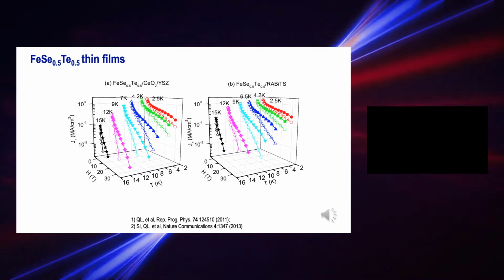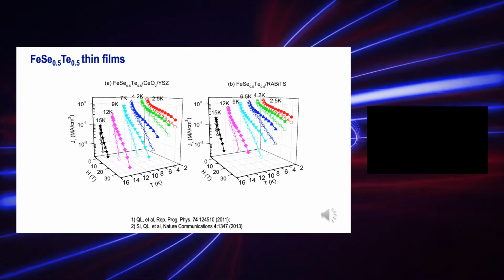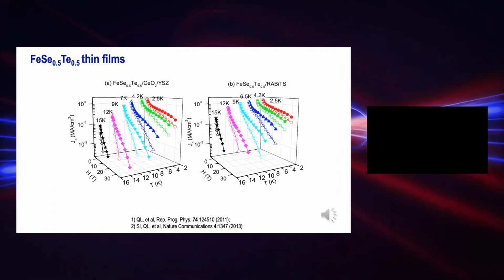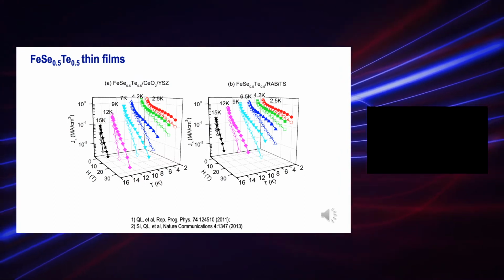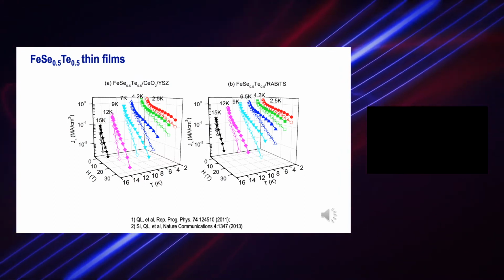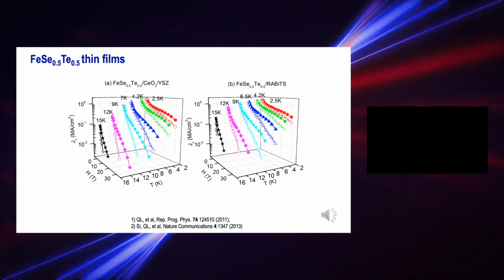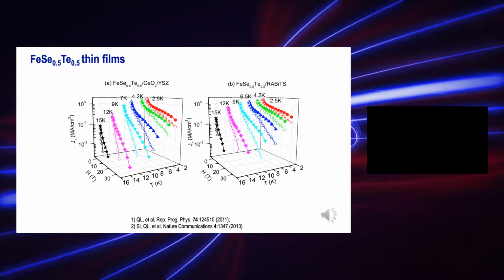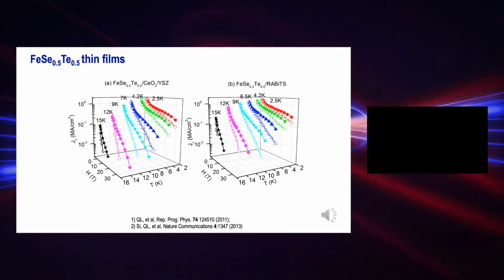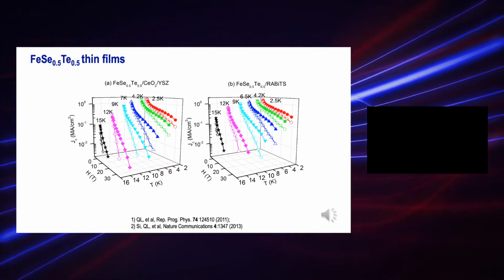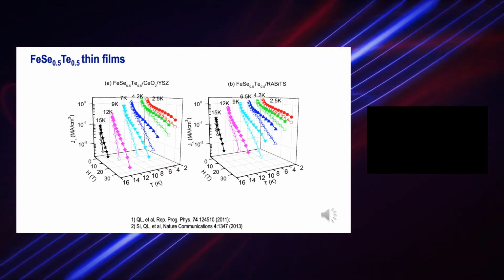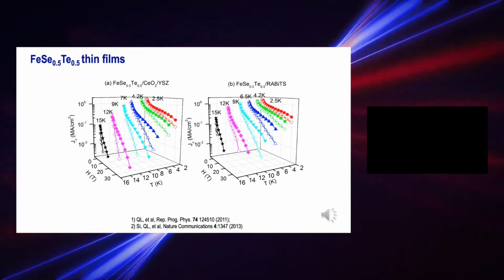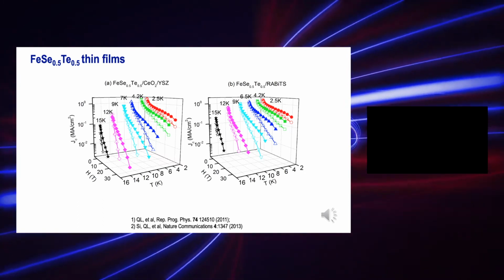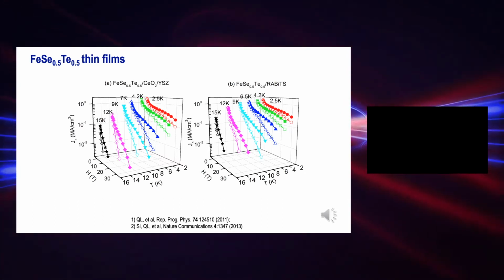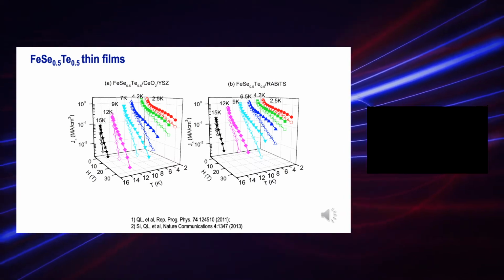We also found these films made with cerium oxide buffers can have a very high current density. Showing here is the plot of the JC as a function of the magnetic field and temperature. Routinely, we can achieve a JC of about 1 megaamp per centimeter squared in these iron chalcogenide films. And this is not only for the films grown on YSZ single crystal substrate, but also on flexible metal substrates such as RABiTS.